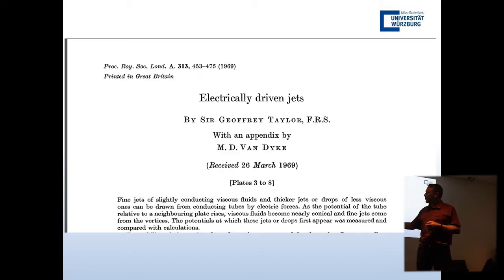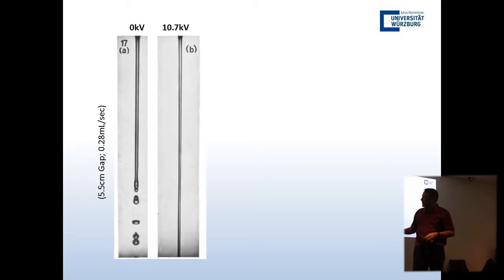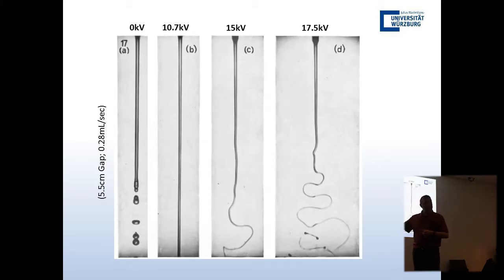This is from Taylor's paper from 1969, and you have water falling with no voltage applied, and it breaks into droplets due to the Rayleigh-Plateau instabilities. And so just before it breaks into droplets, there's a perturbation in the jet. It doesn't remain straight, it actually undergoes a bit of a... There's always perturbations. When you apply a voltage, you actually get a continuous jet. And you keep increasing the voltage, and then you get electrospinning. So there's a slightly different physical effect, and this paper from Taylor in 1969 actually was focused on this.